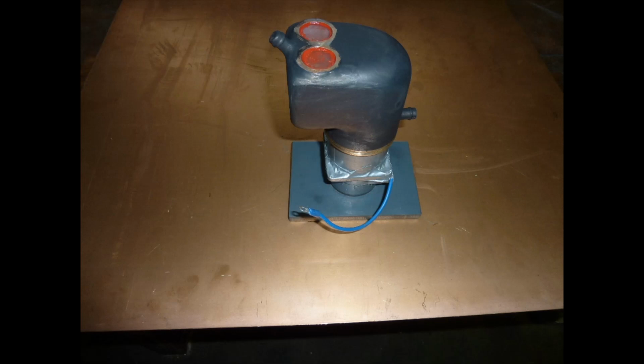Now here I need to jump ahead a bit to mention my first experience of trying to melt out the white metal following plating. This was easily done in the domestic oven, but by having a careful record of weight at every stage, I calculated that about 5% of the alloy had remained stuck inside as a film all over the copper, rather like soft solder might. This didn't really matter, except for the waste of a valuable material. So I sat down to think how to prevent that happening.